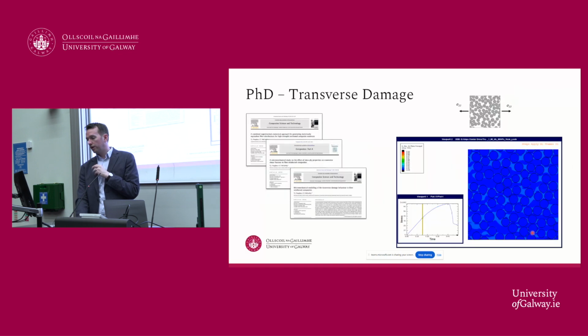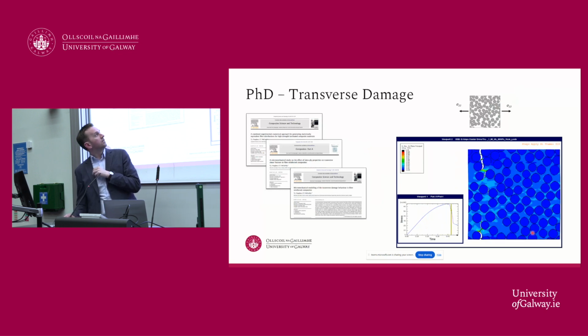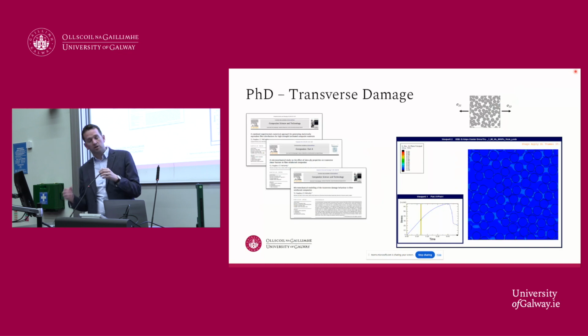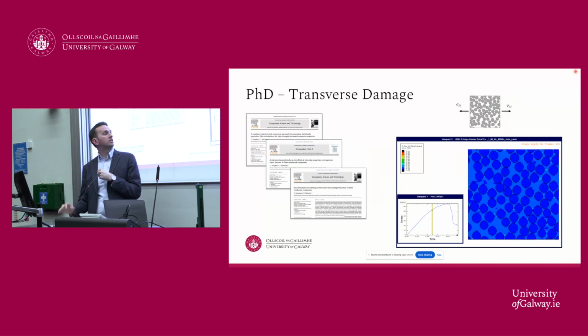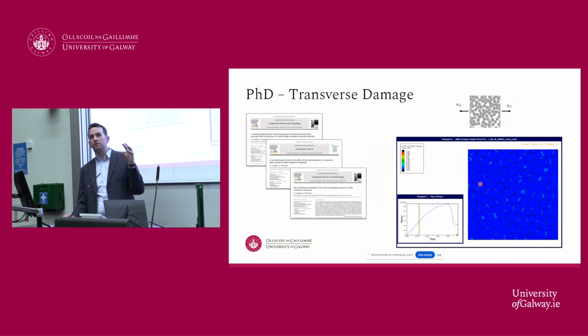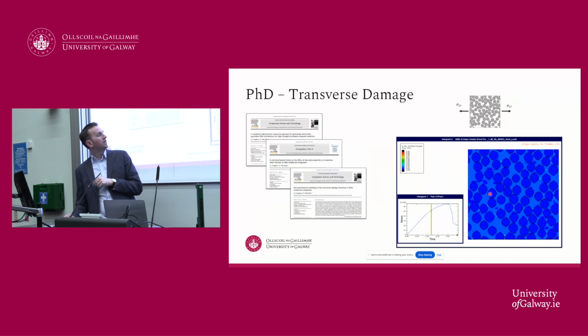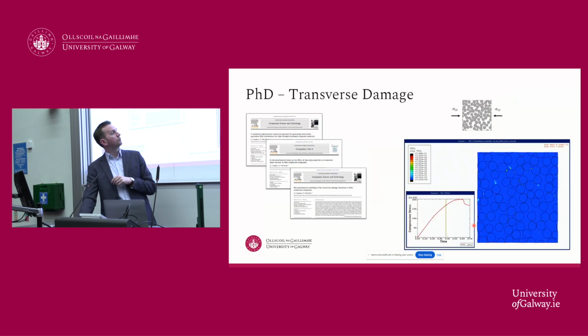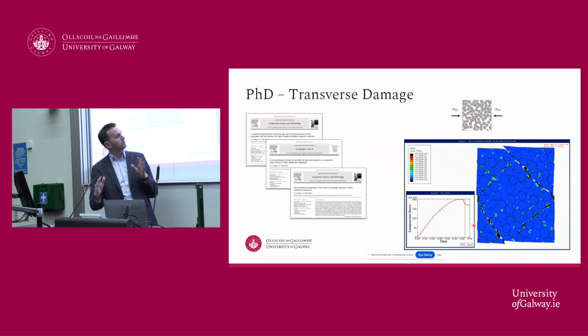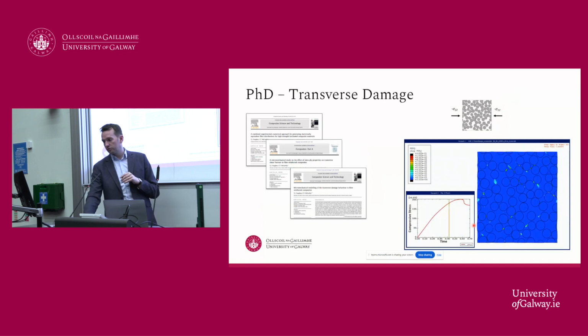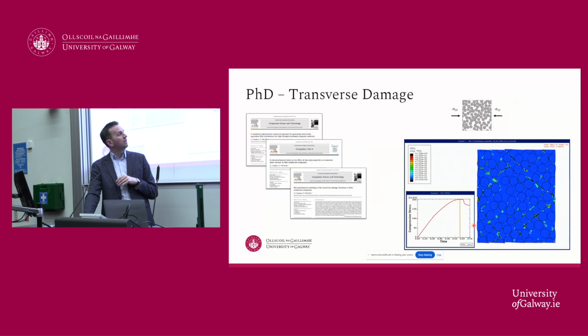In terms of my PhD, I implemented a couple of damage models that were able to capture these processes. We looked at this type of material element being stressed under transverse tension, and we were able to predict the fracture path from that loading. You can see it's recreating the damage mechanism you saw on the earlier slides. We also looked at this under compression. Under transverse compression, the material is compressed horizontally, and you get fracture paths happening through a kind of yielding in the matrix.